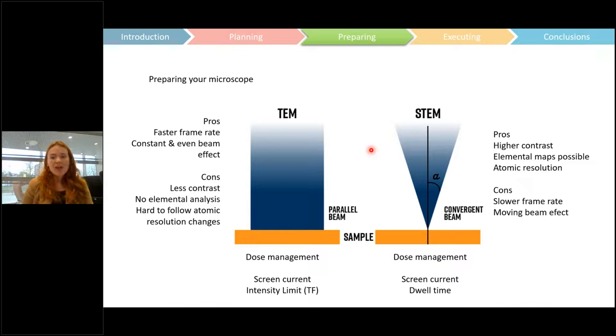In STEM mode, the pros are obviously higher contrast. You get better elemental maps, and you can get better atomic resolution, at least often in aberration corrected microscopes. But the cons are, of course, you have that slower frame rate. You can't acquire as many images per second or per minute as you can in TEM mode, so you tend to miss things. And of course, your beam effect is moving, and it's quite hard to explain that, especially if you have any sort of beam effects going on. It's very hard to know. It's very hard to compare it with the ex situ results.